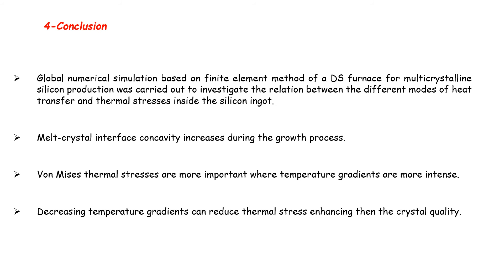In conclusion, this numerical global simulation based on finite element method of a DS furnace for multicrystalline silicon production was carried out to investigate the relation between the different modes of heat transfer and thermal stresses inside the silicon ingot. Melt-crystal interface concavity increases during the growth process. Von Mises thermal stresses are more important where temperature gradients are more intense. Decreasing temperature gradients can reduce thermal stresses, enhancing the crystal quality.